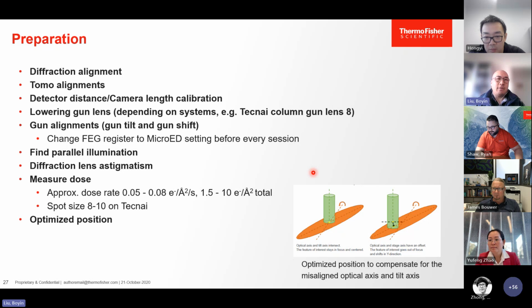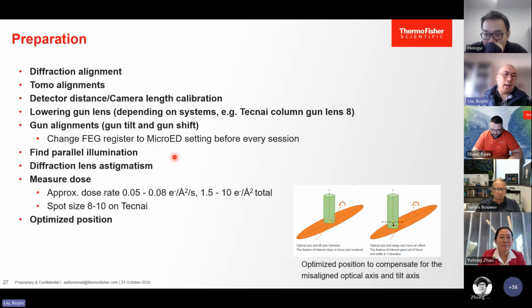For the preparation before you do data collection, of course, some alignments need to be done. The diffraction alignment, Tomo alignments, and the camera length calibration is also very important to calibrate the pixel size. And for MicroED, we can't really use the setup for SPA because we actually use a lower dose for MicroED. So you have to lower the gun lens, and for example, for the Tecnai column, use gun lens 8. We usually use gun lens 8. After you change the gun lens, you need to do gun alignments and save a FEG register, and then find the parallel illumination, and also fix the diffraction lens stigmation.